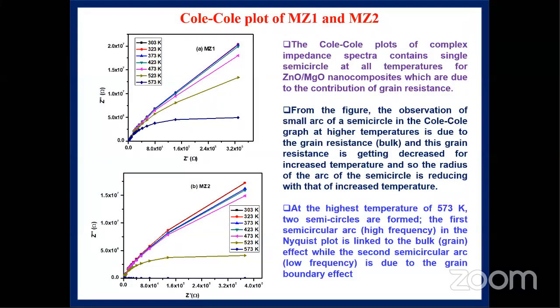You can see the temperature increased from 303 Kelvin to 573 Kelvin. At the highest temperature of 573 Kelvin, two semicircles are formed. The first semicircle at high frequency is linked to the bulk, that is the grain effect, while the second semicircle in the low frequency region is due to the grain boundary effect.